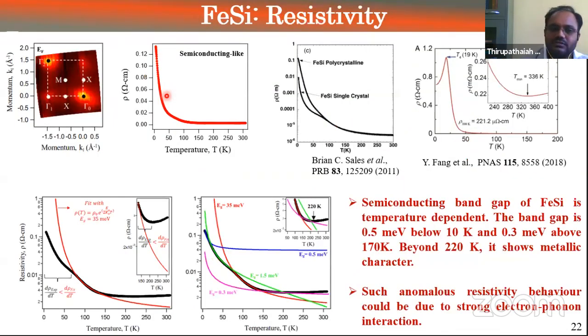And now let me come back to our resistivity measurements, and why we had to do it. As I showed from Claudia Felser's paper, and not only that, in many papers, it was predicted that these systems are in fact insulators or semiconductors. And when we did resistivity measurements, it also suggested to us that this is a semiconductor. Of course, the band gap was very small, 35 meV, but at Helmholtz Zentrum Berlin, with the energy resolution of 1 meV, 35 is really a very big gap to observe. But this map was taken from Helmholtz Zentrum Berlin or BESSY, where we don't see any gap. This is in fact the Fermi surface, so there is no gap.